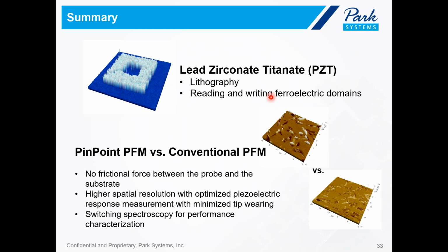So with that, I would like to conclude my talk and briefly summarize what we've gone over today. First, the representative PFM experiment that I showed you today is writing and reading ferroelectric domains with a lead zirconate titanate, or PZT, film. We went over how to do lithography with PFM and also how to write and then read ferroelectric domains with PFM. And then the main take-home point of today's webinar is the performance comparison of conventional PFM and PinPoint PFM. By comparing both the topography and the PFM response images of the PZT film annealed on ITO, the advantages of PinPoint PFM over conventional PFM are very clear.